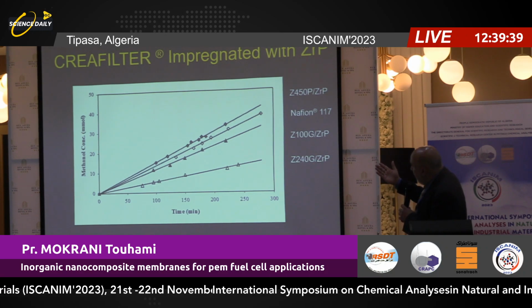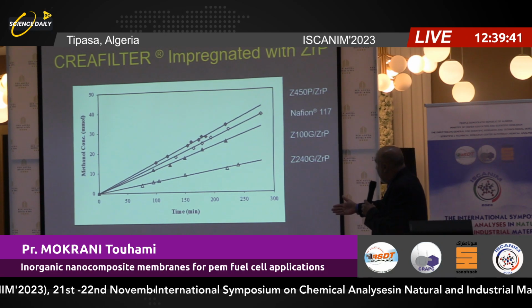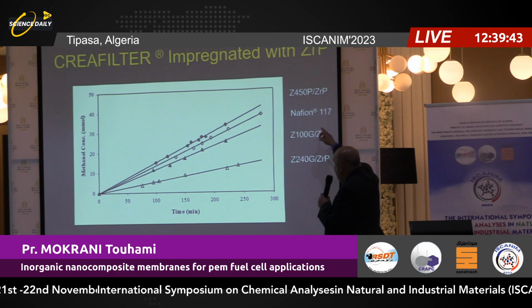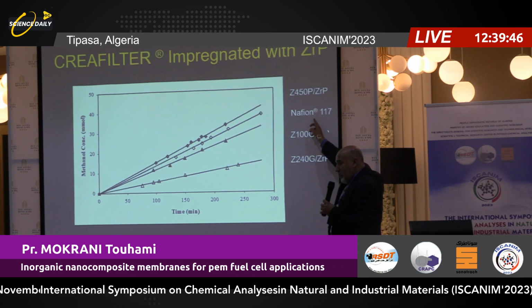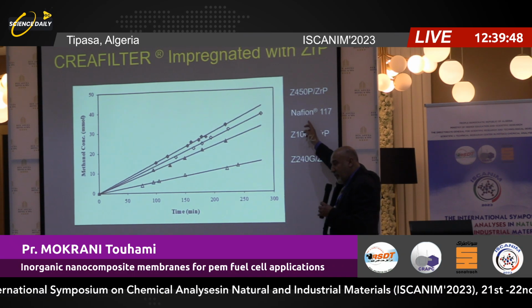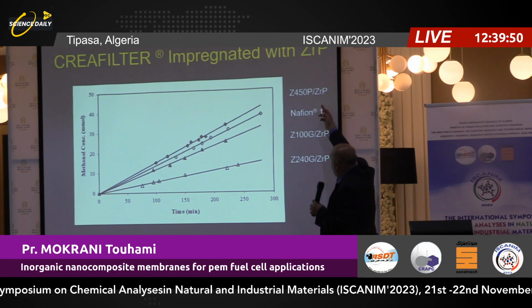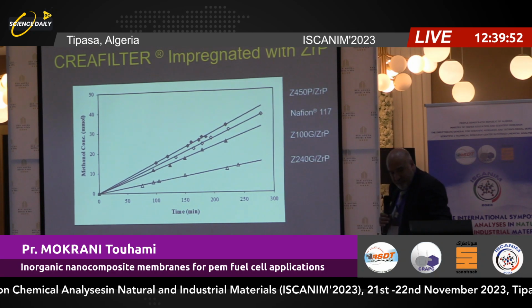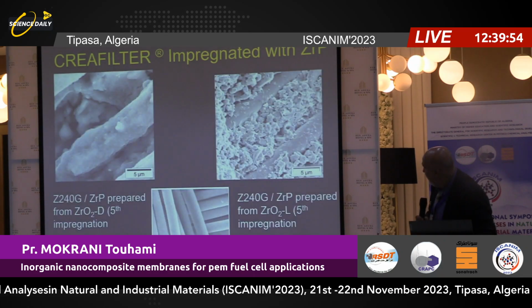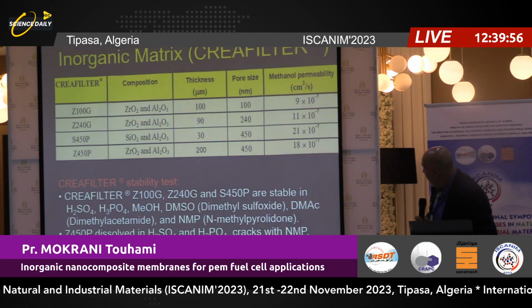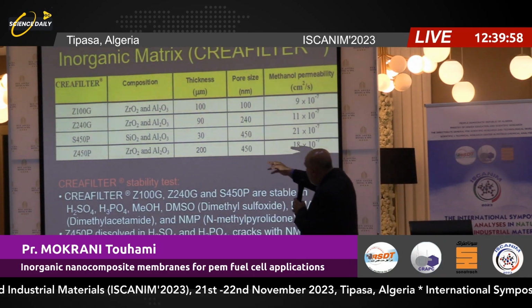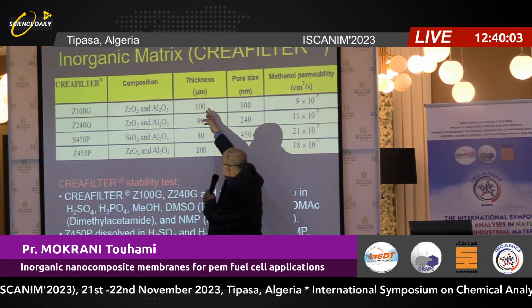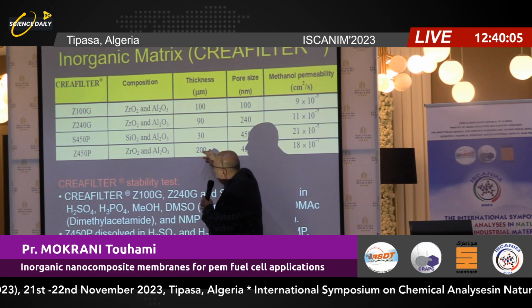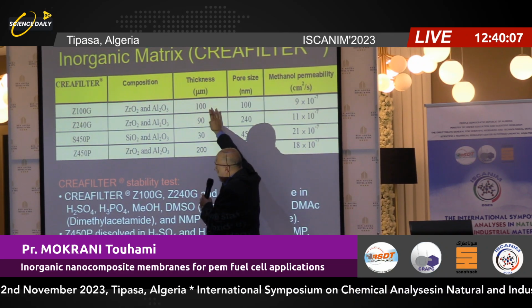Here we see methanol permeability. That's the reference, Nafion 117. Nafion 117 is 175 microns. This material is less. So you can see here, it's 100 microns. Okay, this one is 200. This one is not good. The two ones, that's the good ones.